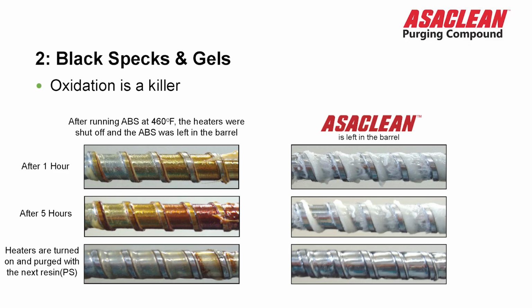And in the bottom picture, after the heaters are turned on and purged with the next resin, you can see that in this particular case, it was polystyrene. You can see that the polystyrene has coated the degradation, but hasn't really removed it. And over a period of time, that's going to continue to build up and create black specks.